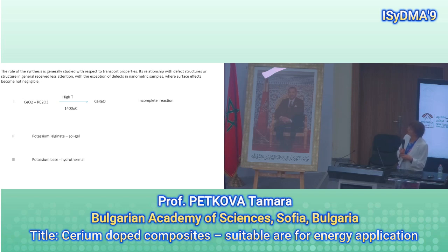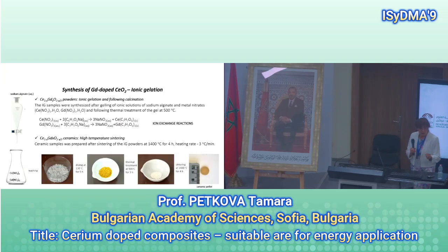We applied several methods. First one, high temperature, the easiest method. We found that the reaction is incomplete, and we stopped with this method. So further we used sol-gel and hydrothermal methods of synthesis. Here is the scheme of synthesis of cerium oxide doped with gadolinium using ionic gelation. Two steps.